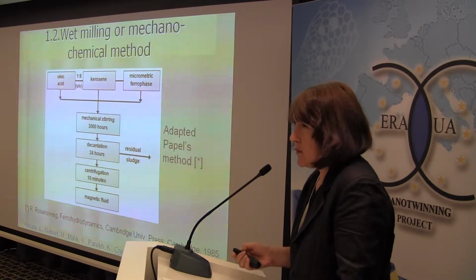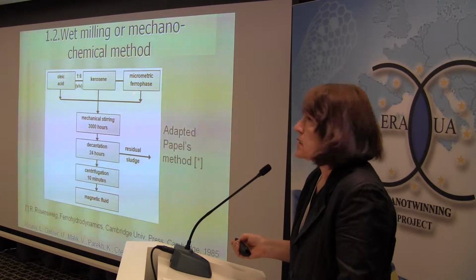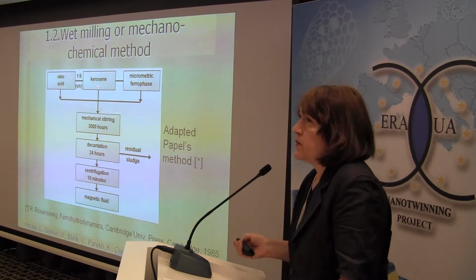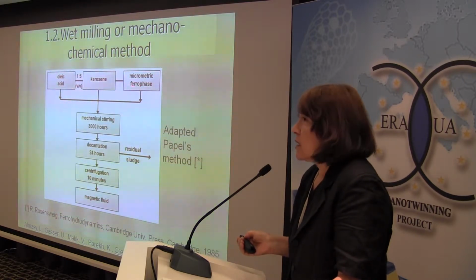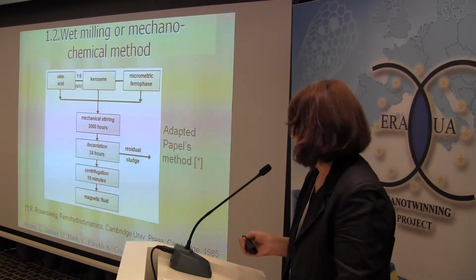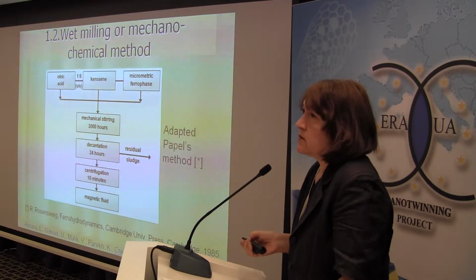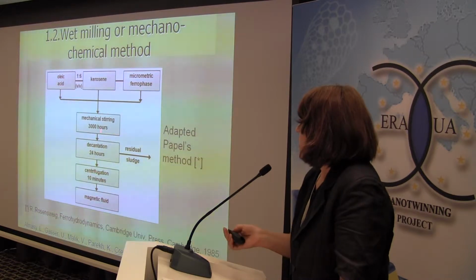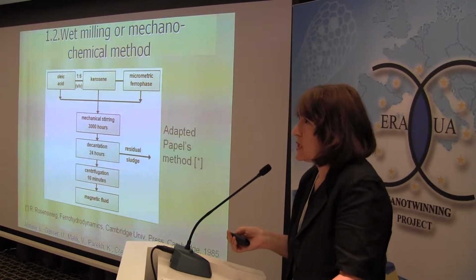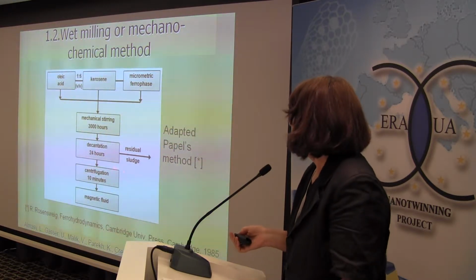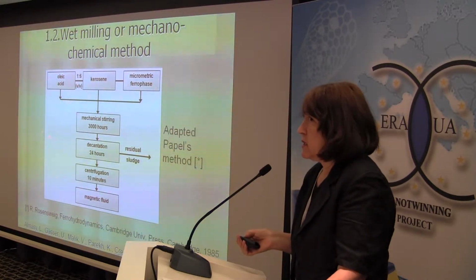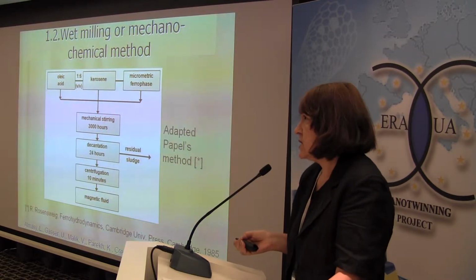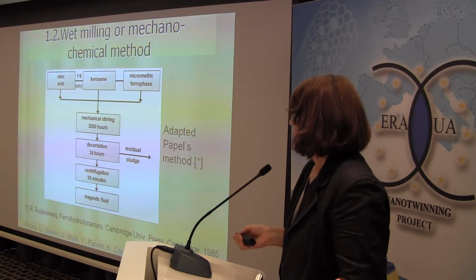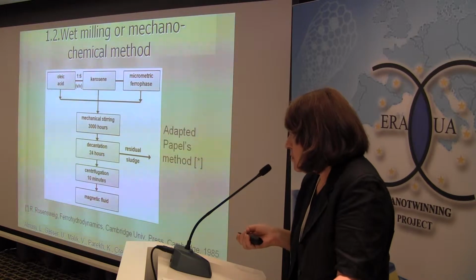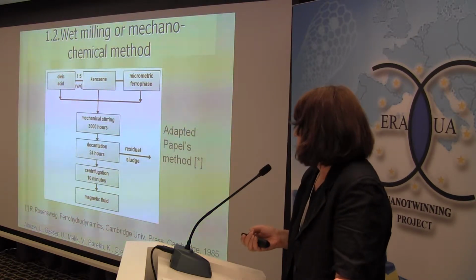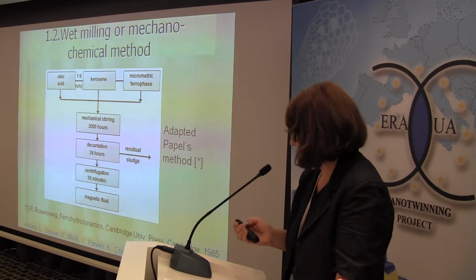The wet milling, or the mechanochemical method, is starting from the ferrophase already prepared of a micrometric size, like those resulted in the charcoal industry as a residual, but rather pure from the chemical viewpoint. The oleic acid and the kerosene are added since the beginning together with this micrometric ferrophase. And then we have to wait for the milling process as long as we need to get good results. This could be a disadvantage, but I believe it is balanced by some advantages regarding the good results that we have obtained, and from the environment protection viewpoint, no chemical spread within the laboratory, and no external heat source needed.